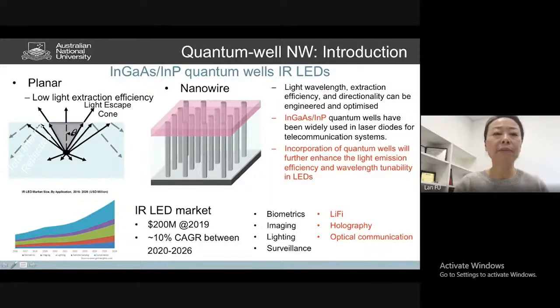Because we know that in a planar device, such as an LED device, due to the internal reflection effect, the light extraction from a planar structure is actually limited. So if you have a quantum well inside an LED structure to enhance the efficiency, it can emit light very efficiently. However, because of this planar structure, the light is very hard to escape. So normally, light extraction efficiency from an LED is very poor, like 10% or something.